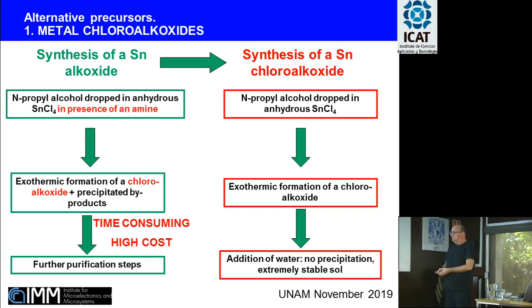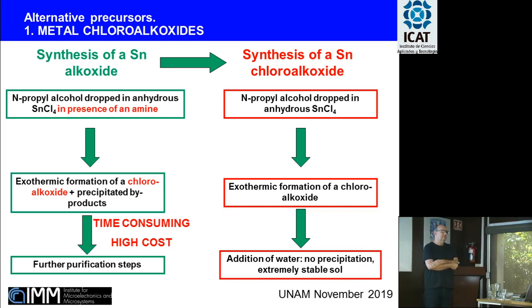What is the problem with this procedure? If we want a pure alkoxide, it is necessary to eliminate these chloro groups which are bonded to the central tin, for instance. And this purification procedure is very long and expensive, so that the final tin alkoxide is extremely expensive. Also, I remember that once we bought some tin alkoxide for making some comparison, and it was extremely unstable. You make one solution, you use it one day, it is very expensive. The day after there was some precipitation in the container, so it's not very convenient.